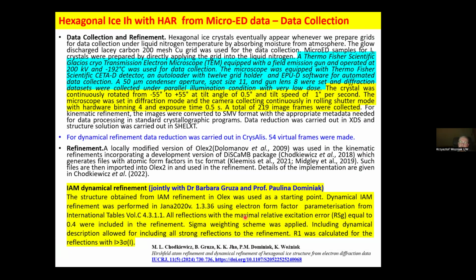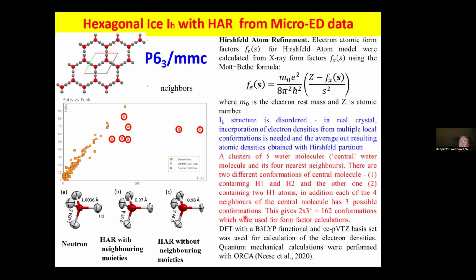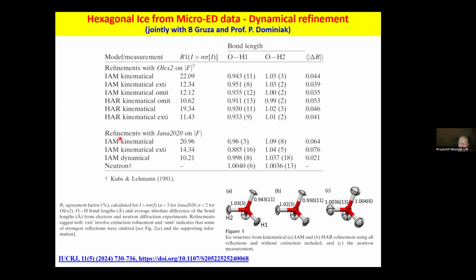We also performed hexagonal ice studies using microelectron diffraction data. Here's a description of technical details. We've also done dynamical refinement of this. Fortunately, there is a simple relation between X-ray scattering factors and electron atomic form factors, and it's given by this relation, the Mott-Bethe relation. So we use this, and the quality of the electron diffraction data we obtained with our Glacios diffractometer. We performed refinement using firstly kinematic refinement and then Hirshfeld atom refinement using the kinematic outcome as a starting point. And we've got pretty good results.